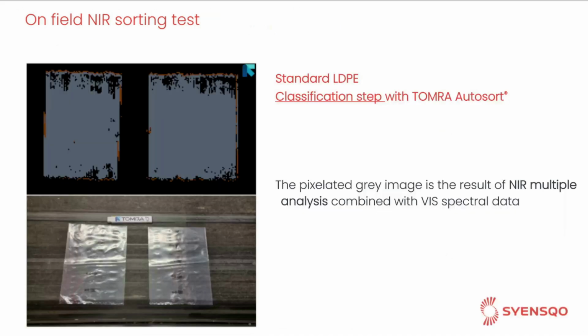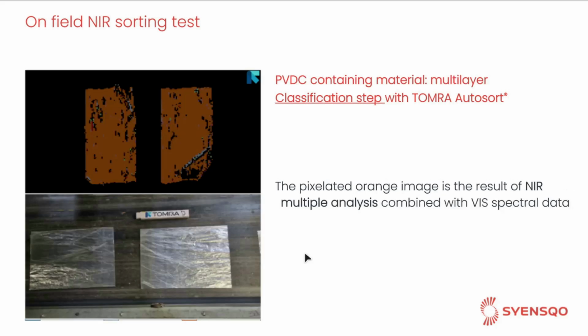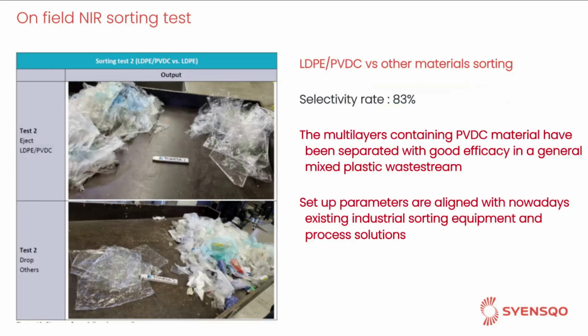And the first thing that we performed was a classification step with this equipment, giving the right references for the database. This here is the simple image of the polyethylene, and the pixelated gray image that you see on the upper part of the slide is the result of near-infrared analysis combined with the visible spectral data. The important point is that we also included our multi-layer structure, the 5-layer containing one layer of PVDC. In this case, again, the orange image that you see for all the objects included in the data set is the result of near-infrared and visible spectral data.